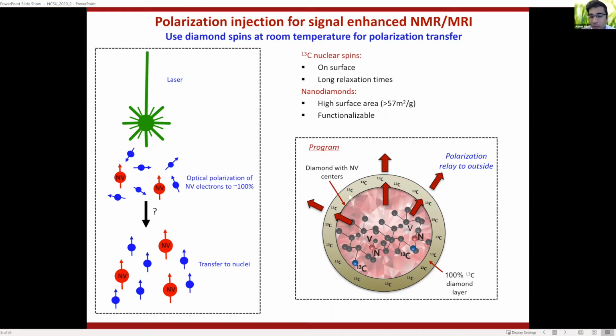So this is a cartoon, but you can take a diamond particle and grow on it C13 diamond. So you can make a diamond on diamond growth. And this could be enriched with C13. So you can have 100% C13 on the surface, a very high concentration of C13. They also are very coherent and have very long relaxation times. So you can get all the nice properties of nuclei. Apart from that, you can have very high surface area, and these particles themselves can be functionalizable, so you can move them wherever you want physically.